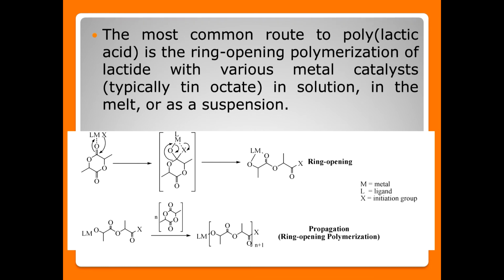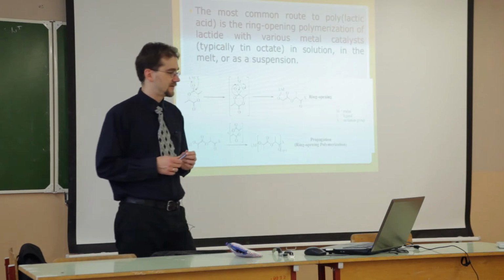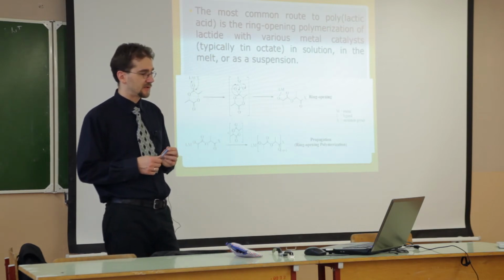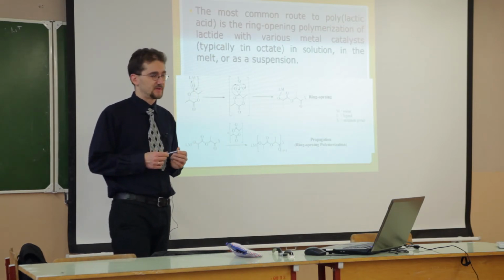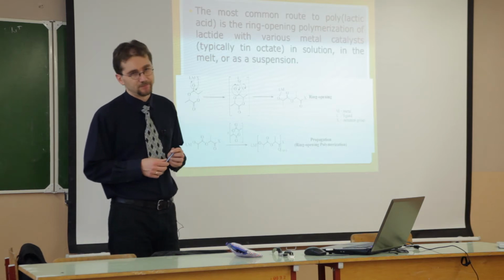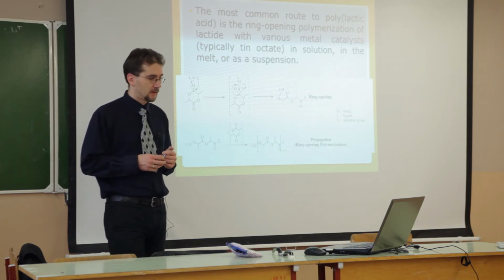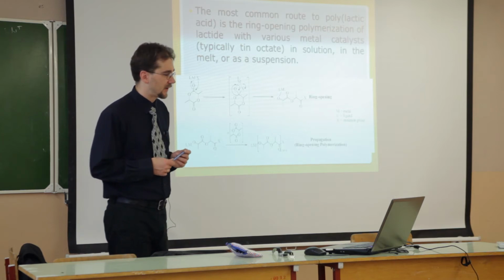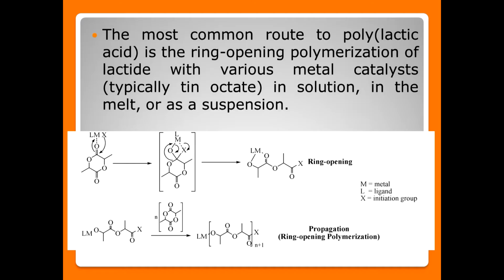The most popular, most common way for polylactide production is the ring opening polymerization of lactide, and mostly it is necessary to use different catalysts, typically tin octoate. It can be made in solution, in melt, and as a suspension.